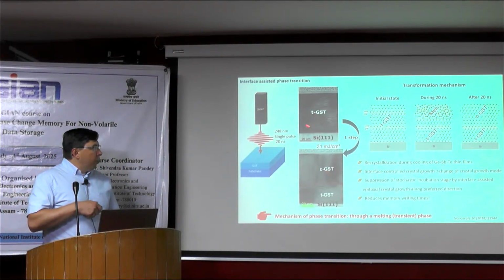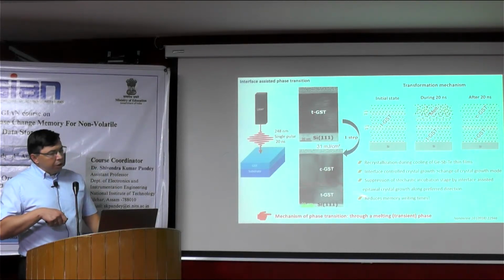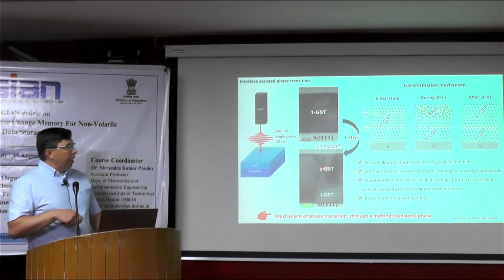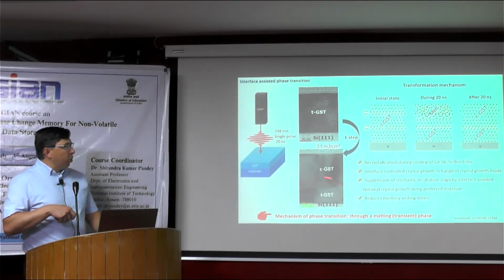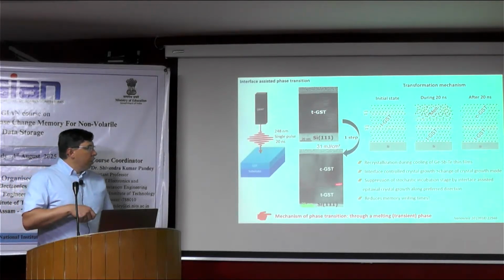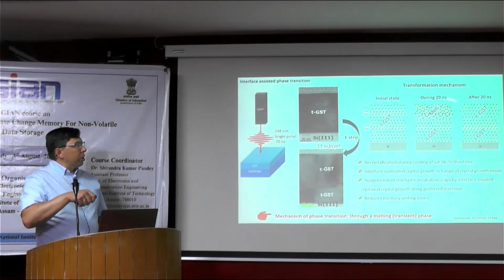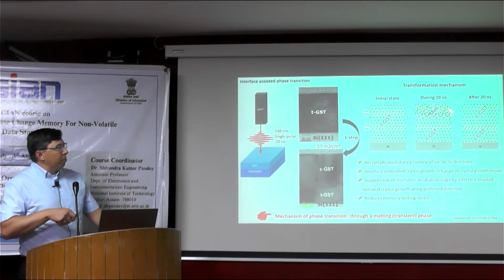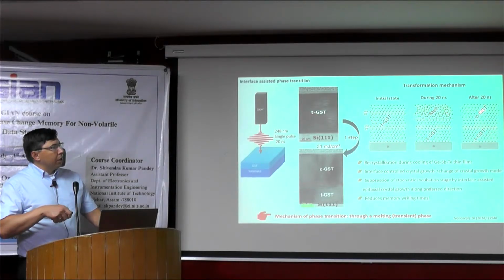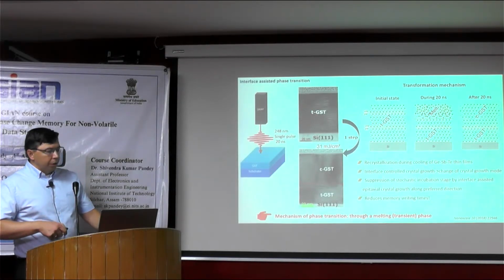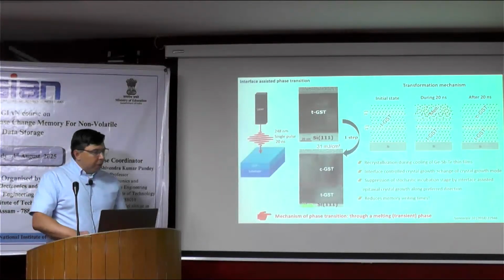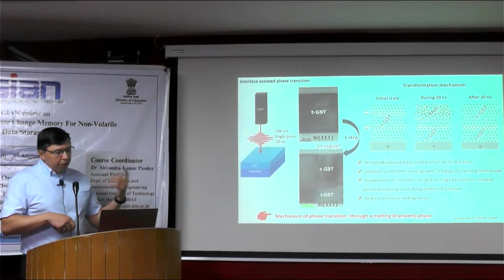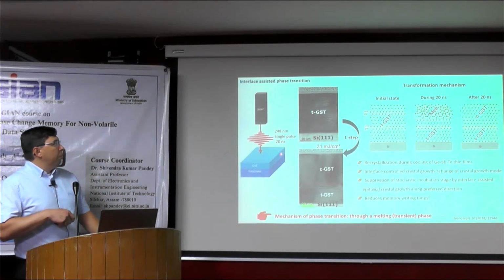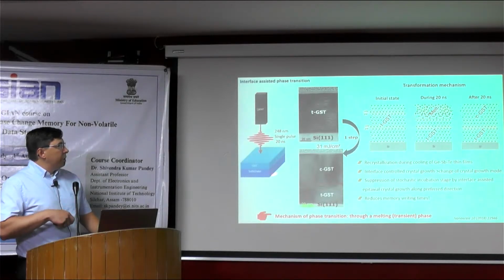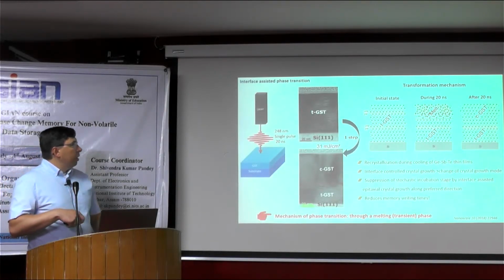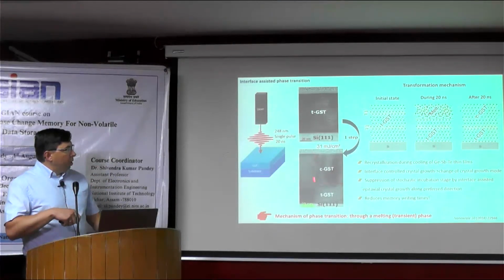Interestingly, although there is a template in the case of TGST, and we would assume that the vacancy layered phase, or TGST phase, could be formed here, it's not formed. Somehow during this process the system forgets about the previous structure, and then there is a transformation to the metastable CGST phase. It can also be used for multi-level data storage: if you adjust the pulse duration or the energy of the laser, we can adjust the volume of the transformed phase.